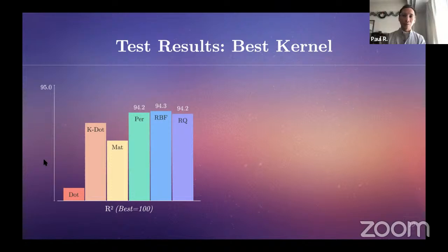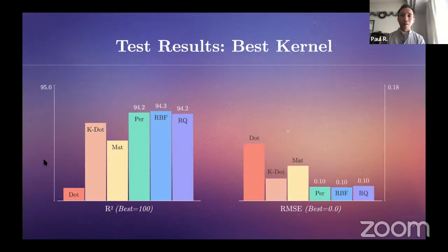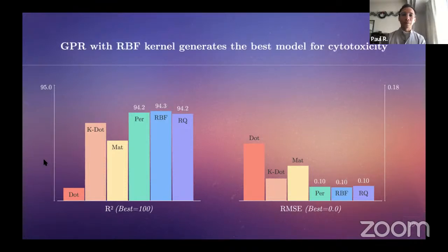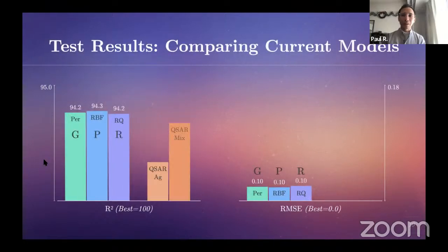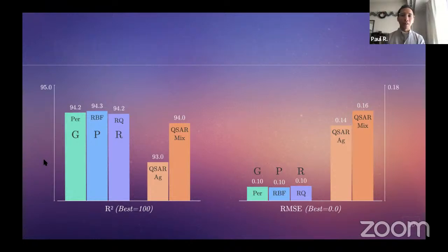We tested a total of 6 types of kernels: the dot product, constant multiply dot product, Matern, periodic, RBF, and rational quadratic. Out of these 6 kernels, RBF has the highest R squared score of 94.32, followed by periodic and RQ. In terms of RMS error, RBF also scores the best, with the least RMSE score of 0.10, again closely followed by periodic and RQ. Comparing our model to the QSAR models of Mikolajczyk et al., our GPR model outperforms in both R squared and RMSE scores.